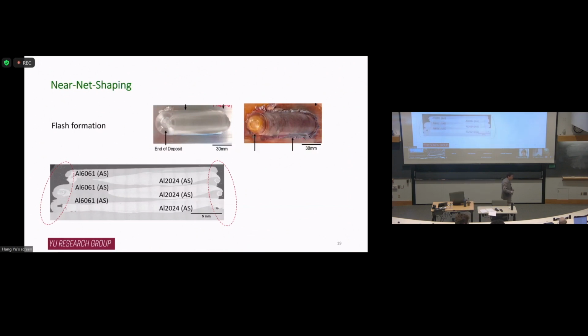Of course, we have limitations as well. So what's our limitation? This is a deformation-based process. As I explained earlier, I have a material getting yielded and being extruded to the side. Once the material is on the side, especially at the edge of the deposition track, the compression is low, and there's not much mixing between the deposit material and the substrate. So the edge is of low quality. The edge of deposition has low quality, and sometimes you get pretty rough edges.